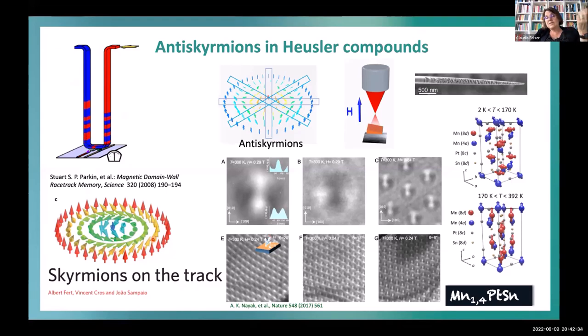Here, even in the Heuslers, nearly all of the tetragonal ones show interesting skyrmion behavior, which you can measure with Lorentz TEM. You have to fit such a needle, and the size of the skyrmions strongly depends on the thickness of the needle. You see this nice feature, and this is very nice work of Ajaya, who started it and is at NISER. I think he's also continuing to work on this.